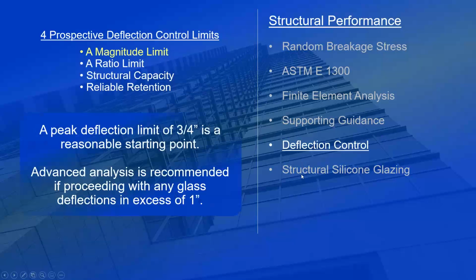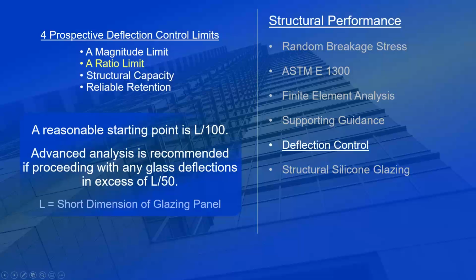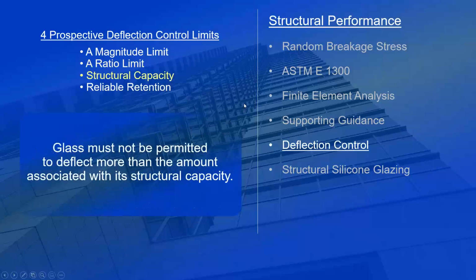Let's talk about deflection for a moment. Generally, as a safe guideline, a peak deflection limit of 3/4 of an inch is a reasonable starting point. Advanced analysis is recommended if proceeding with glass deflections beyond 1 inch. Many of Guardian's customers will limit deflection to about 1 inch. However, with the onset of oversized jumbo glass, over 50 square feet, over 100 square feet, we are seeing deflection in excess of 1 inch, sometimes 1.5 inches, sometimes more. It's always looked at on a case-by-case basis. So a reasonable starting point is L over 100, but advanced analysis is recommended if proceeding with glass deflections in excess of L over 50.